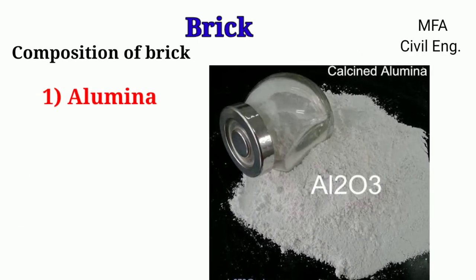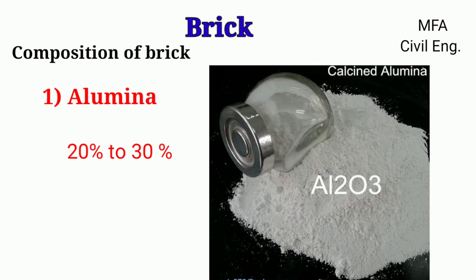Alumina is a chief ingredient of every clay. It absorbs water and imparts plasticity to the clay, so bricks can be easily molded. A good brick earth should contain 20 to 30 percent of alumina. Note that excess alumina makes bricks liable to shrink during drying and burning.